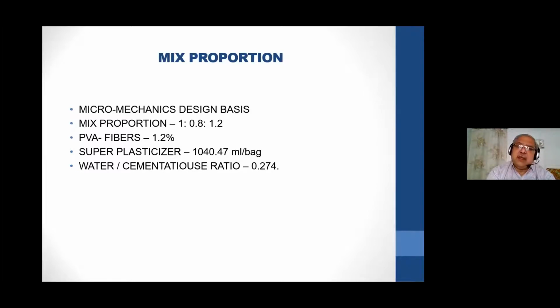The mix had cement, then fly ash, and then fine aggregate. We started with so many things. Ultimately, 1.2% fibers by volume was quite qualified. The superplasticizer used was 1040.47 ml per bag, and the water cement ratio was kept very low, at 0.274.